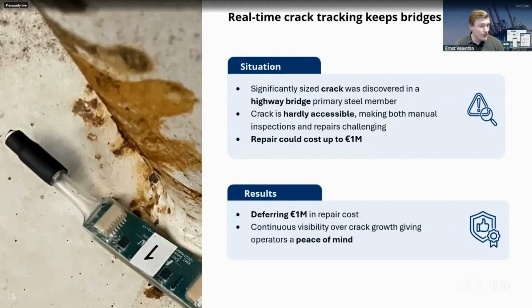So that's where we were brought in, and we applied our sensor system both to these existing cracks in a reactive fashion, but also to the same structural members a bit over on the bridge, so the repeated details there, to be able to flag any newly occurring crack growth there very early. The system was installed, calibrated, and after a long period of monitoring, I think now about 2 years, we are still not seeing any continuing crack growth from this location, which has now led this asset owner to also believe that these cracks were mainly due to defects in the manufacturing and not necessarily due to fatigue stress already causing this damage in the bridge.